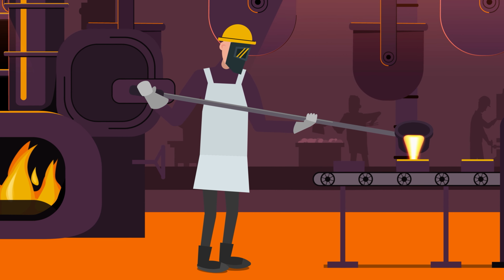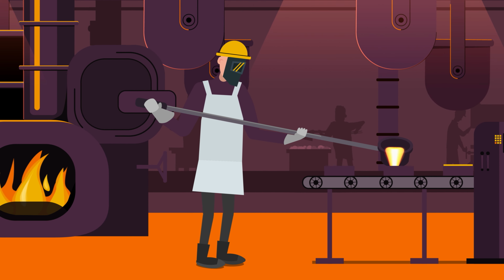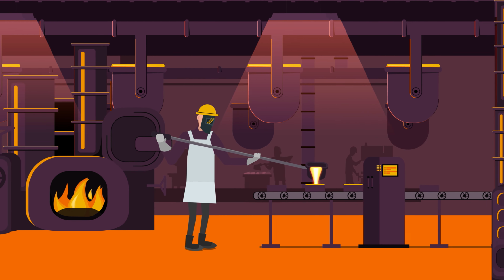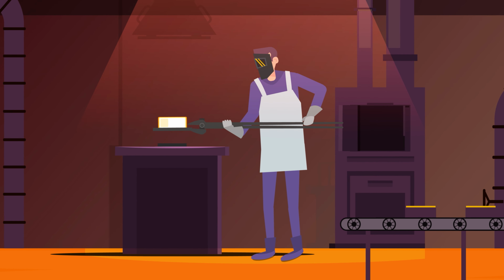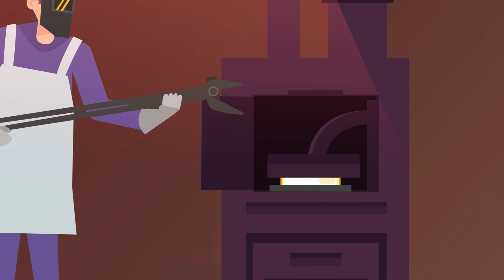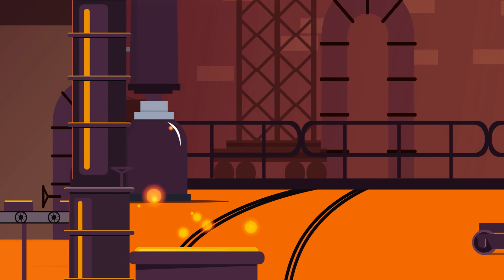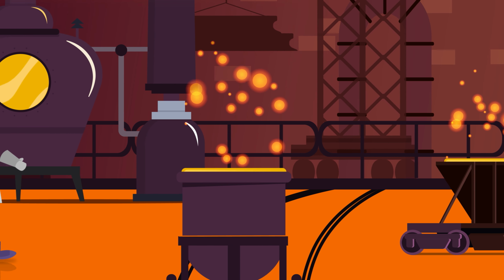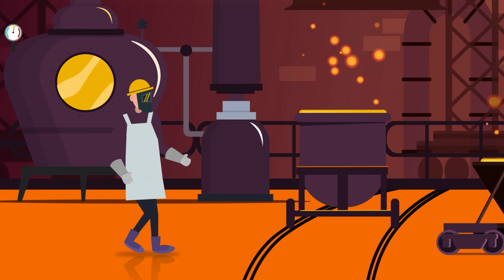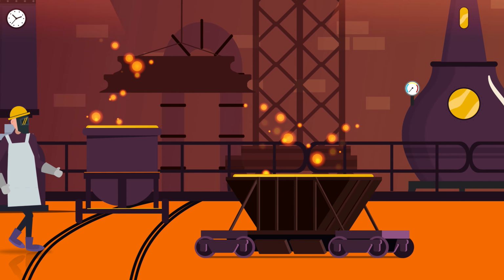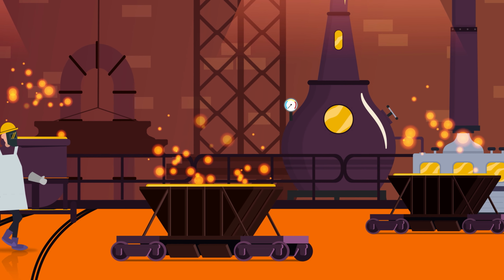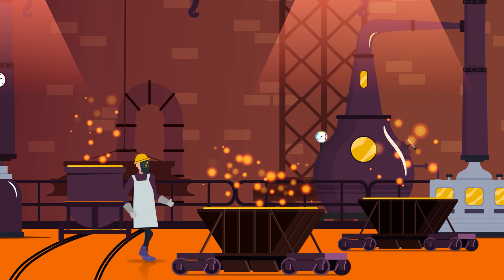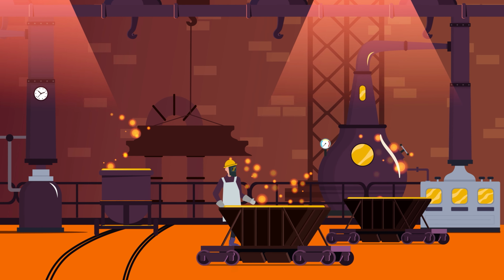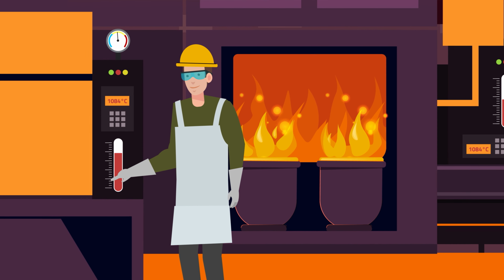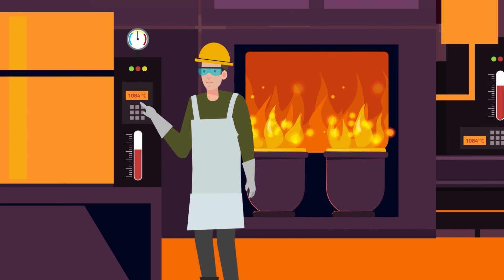Throughout this process, samples of the copper are taken repeatedly for precise analysis. Once the valve is opened, these samples are cooled under pressure. After cooling, they are sent for analysis to determine the copper content. The smelting process is a precise and dangerous operation, with each step carefully controlled. Only the smelters are permitted to move freely, as the red-hot slag, although containing iron, is much lighter than copper. This causes the slag to float to the surface, where it is skimmed off.